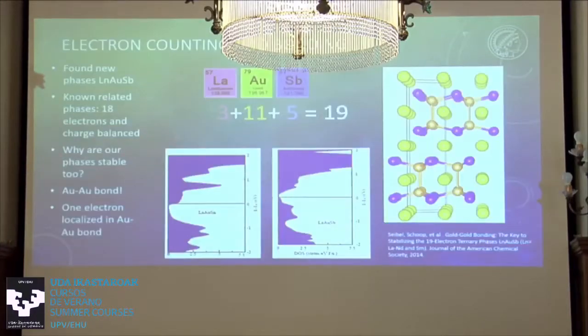While electron counting to 8 or 18 really often works well, it doesn't always do the complete trick, sadly. Otherwise, the chemistry would be way too easy if you just needed to know how to count to 8. So this is a story about a phase a friend of mine was working on during my PhD. She said she found a new stable phase, lanthanum, gold, antimony, with a composition of 1-to-1-to-1, and mentioned it to me because I was working a lot on 1-to-1-to-1 phases.